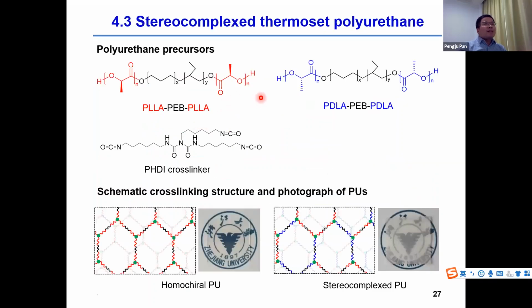We further extend our study to the thermoset elastomer. In this case, we cross-linked the PLA and PDLA triblock polymers by a cross-linker using the well-known polyurethane chemistry. The ratio of PLA and PDLA is controlled in the network. The homochiral polyurethane network containing only PLA or PDLA blocks is non-crystallizable and transparent. However, the polyurethane containing both PLA and PDLA blocks is crystalline and not transparent.